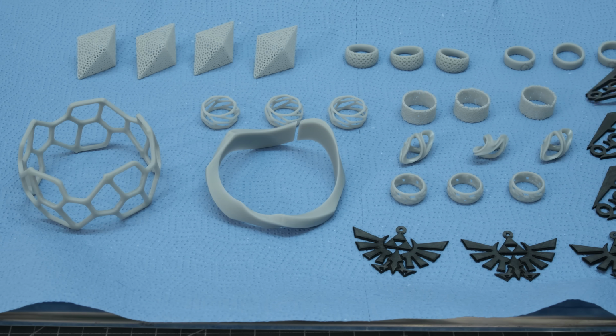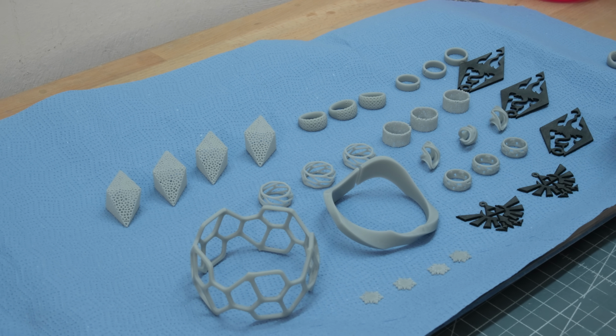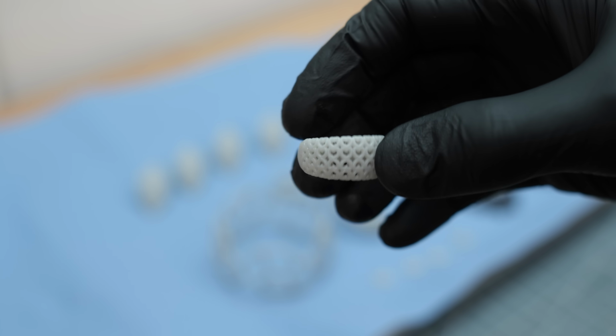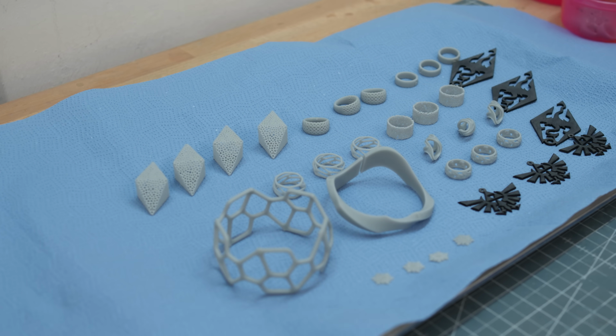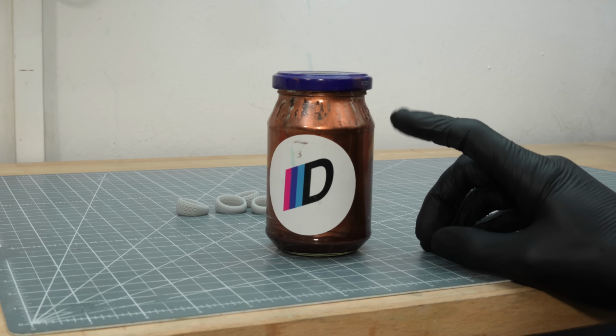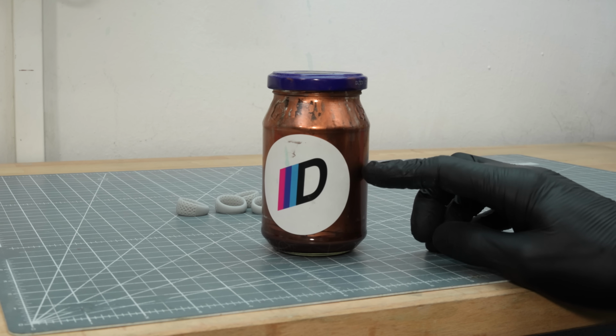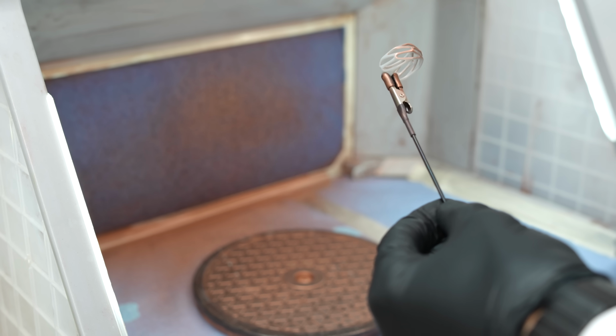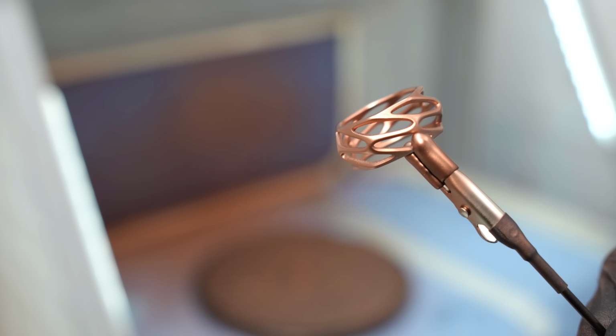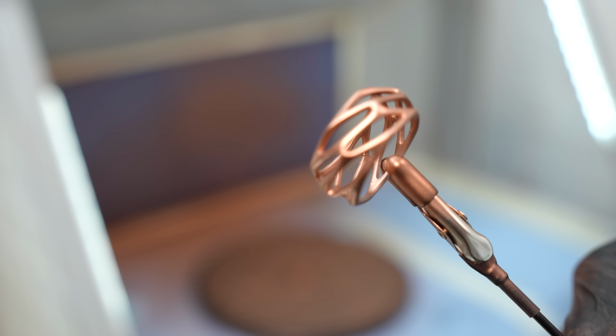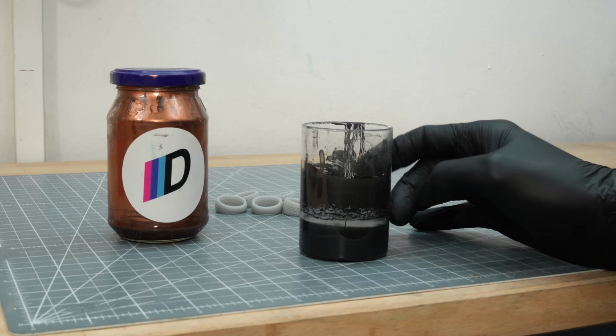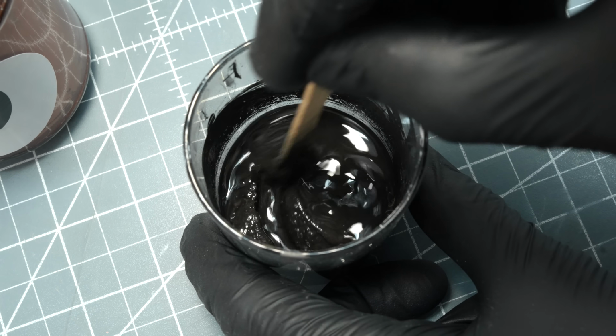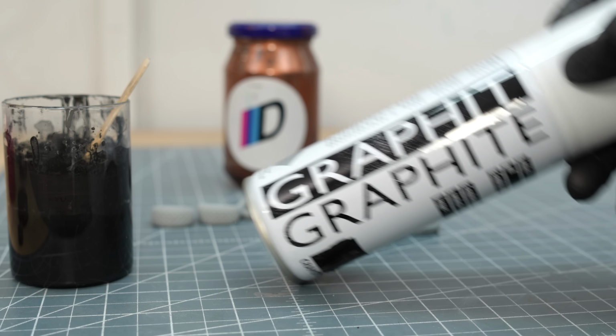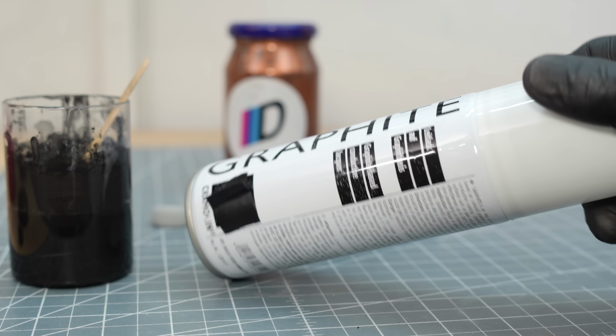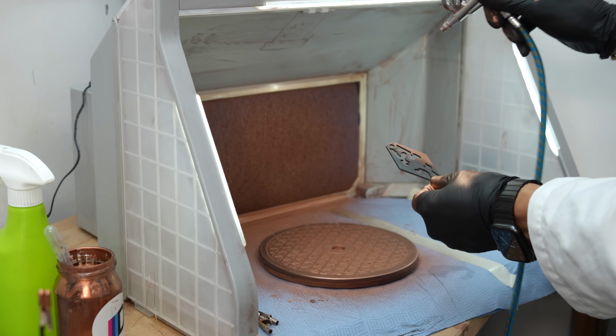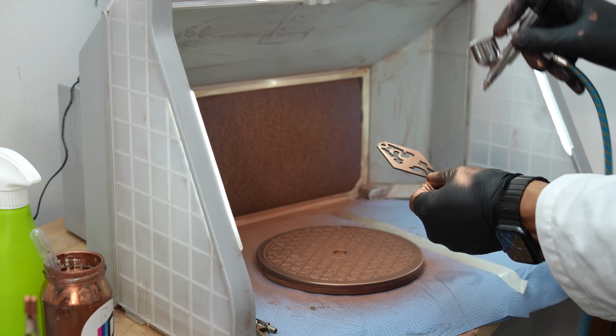Once you're confident after hours of sanding that the pieces can't get any smoother or more even, it's time to make them conductive. This is a prerequisite and we have several options for achieving it. If you can get your hands on it, conductive copper paint is a great choice. It can be thinned and applied with an airbrush. The second option is DIY graphite paint, which is also airbrushable when thinned. Lastly, there's the ready-to-use graphite copper spray. All three methods work fantastically when used correctly, each with its own pros and cons.